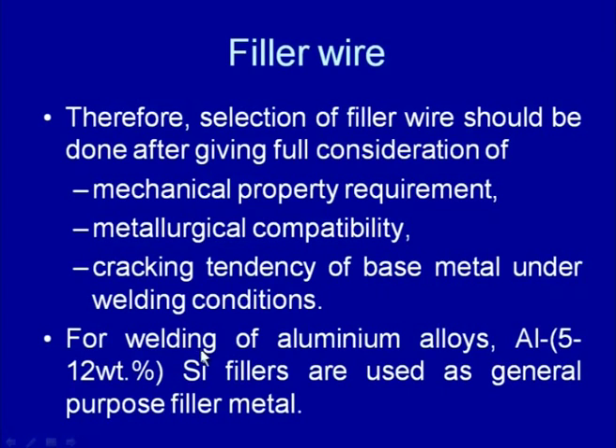For example, in the welding of aluminum alloys, we frequently use aluminum silicon filler material, where the silicon content can vary from 5 to 12%. This is very commonly used and very much preferred because of the very low melting temperature it requires, the very good fluidity of the aluminum silicon filler materials, and the very good properties it offers in carrying the load and as far as performance of the weld joint is concerned. So, the use of aluminum silicon filler materials in aluminum welding is very common for welding different types of aluminum alloys.